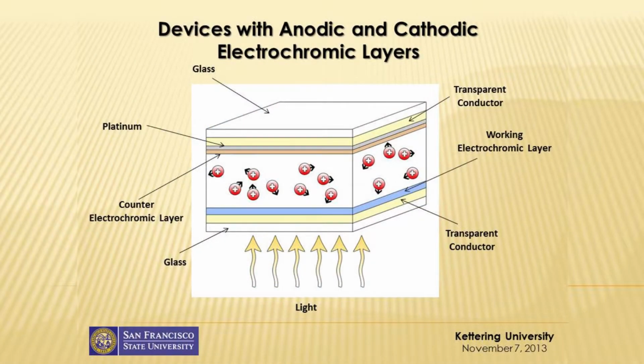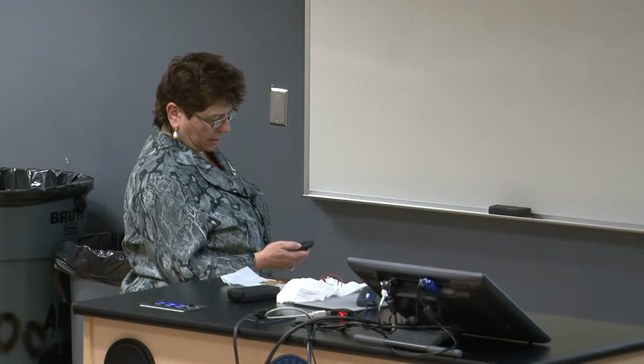And then we use the counter electrochromic layer. That should be the oxidized, that should be the anodic electrochromic material. And we have mobile ions in the ion conductor. This is the ion conducting material. And then we have a working electrode, which is the cathodic electrochromic layer. So that's the sandwich structure of the device that you've seen in this prototype. It's exactly the same structure.